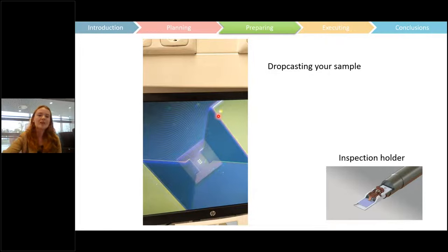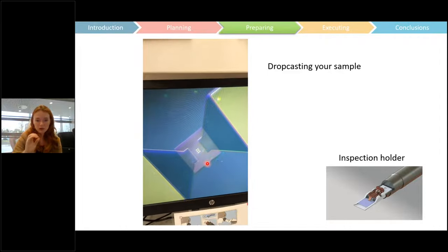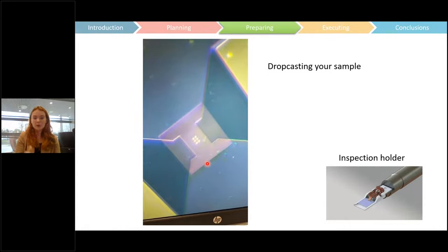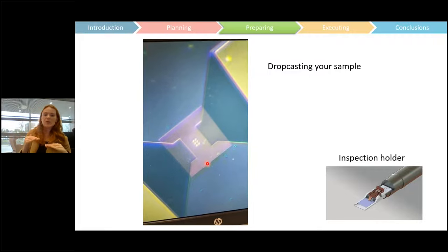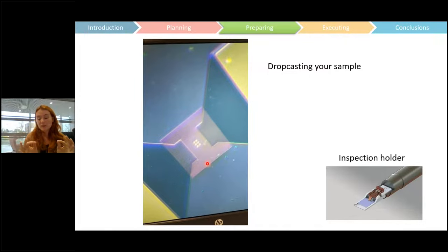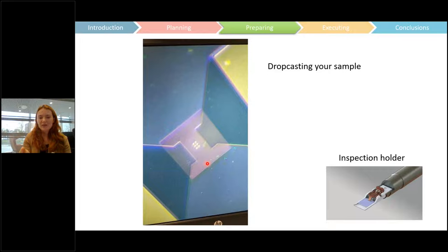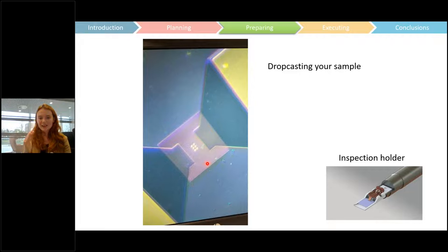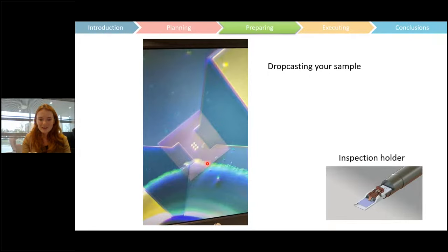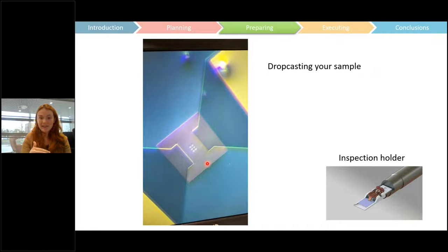The way we do that is we use a stereo microscope, which you can see the screen of here. This has the chip that we are going to study. And here you can see the windows with the six little holes. My colleague in this video is going to drop cast the sample onto the chip. If you have the right lighting, as the ethanol evaporates, our drop casting solution is usually in ethanol, there will be surface tension on the liquid, which will reflect light. That means you can see where the sample has landed.